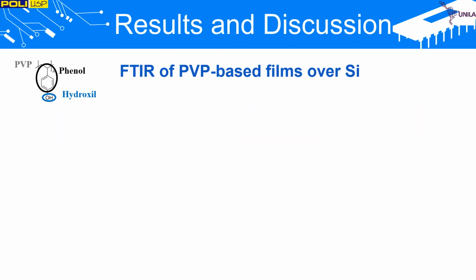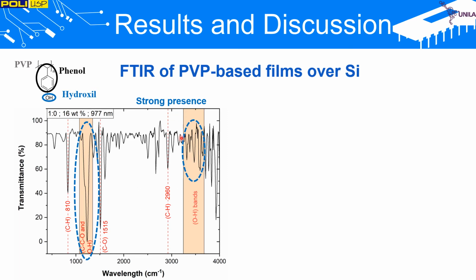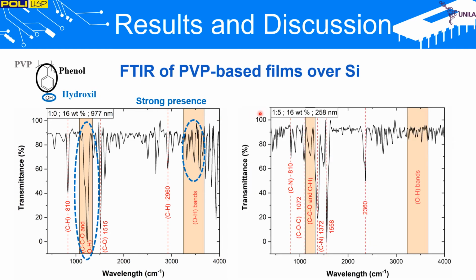In this slide, let's see the results of thin film characterization by FTIR spectroscopy. The molecule of PVP is composed of the hydroxyl group, which has a strong presence without cross-linking with PMF. That can be seen in this graph. Once the molecule of PMF is added at 1:5 ratio, then the hydroxyl group bands tend to decrease, and in some cases disappear, which indicates that the cross-linking occurs.